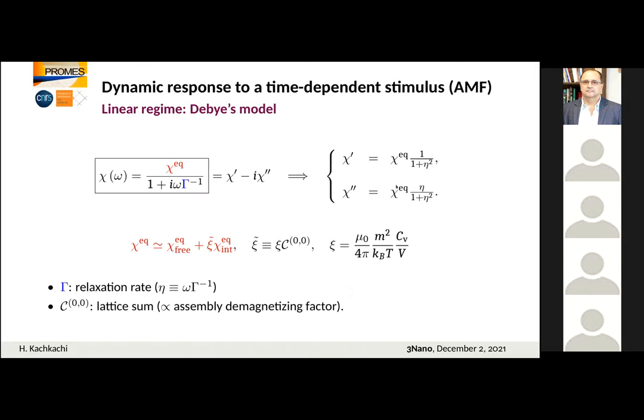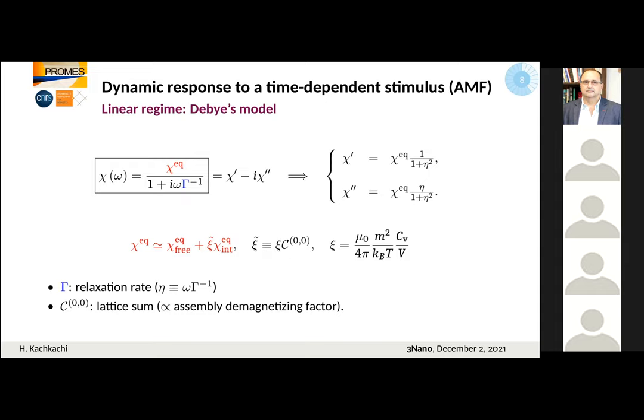Well, let's consider the simplest case. Let's drop higher orders and stay in what's called the linear regime. In this case, we may use the well-known Debye model, where the susceptibility can be written as the ratio of the susceptibility at equilibrium divided by this quantity, where gamma is the relaxation rate, or gamma inverse is the relaxation time. If we write this susceptibility as a real part and an imaginary part, we can obtain the real component and the out-of-phase component.